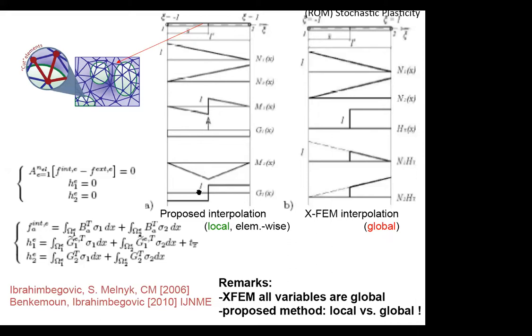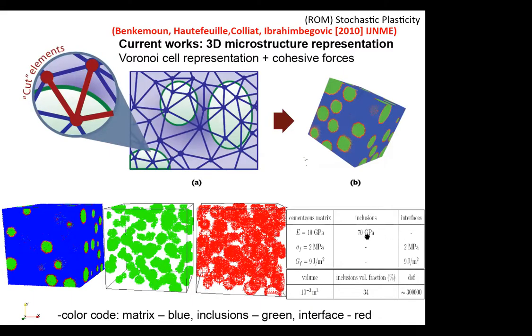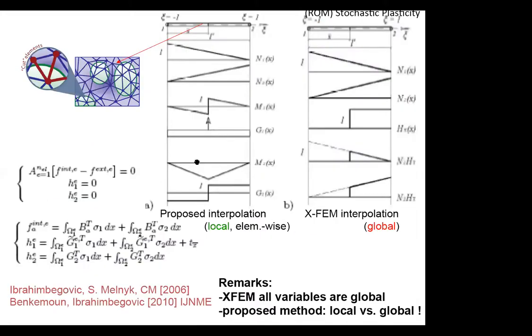And for this one, we need also discontinuity of the strain field, because here, for the constant stress, you have 2 different materials. So strain has to have a jump, because simply you're dividing the same sigma here by E1 and here by E2, E1 being the Young's modulus of aggregate, which is 7 times bigger than Young's modulus of cement. So strain cannot possibly be the same. So when I do this, I have a so-called embedded discontinuity model, which has a representation of fracture given here, but it also has a representation of total strain field to handle the heterogeneous material that happens to be used in these cohesive links. Interestingly enough, I have 2 extra parameters, and I get, that was your question after the